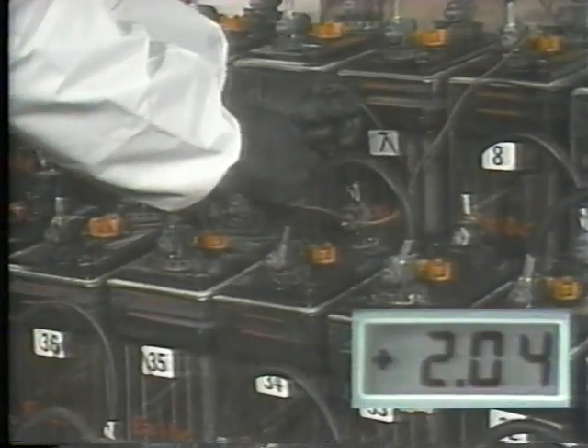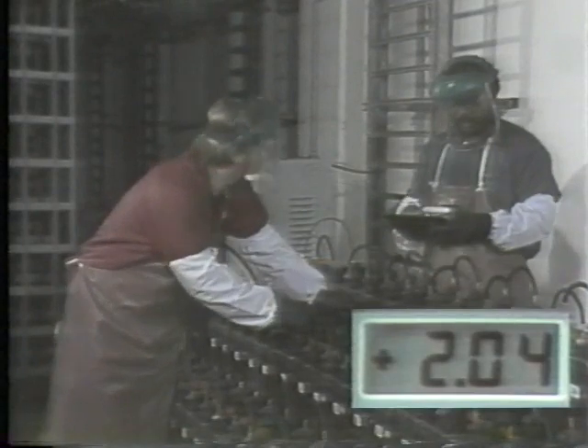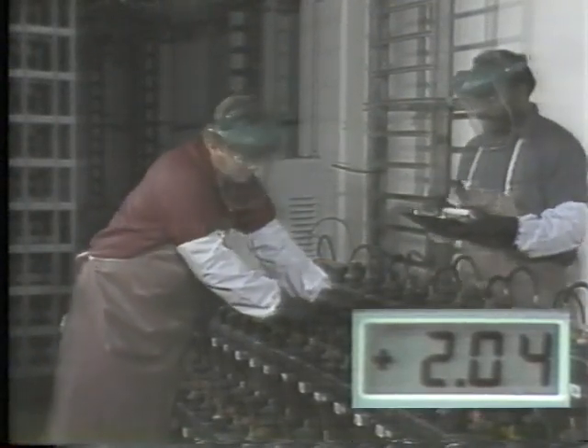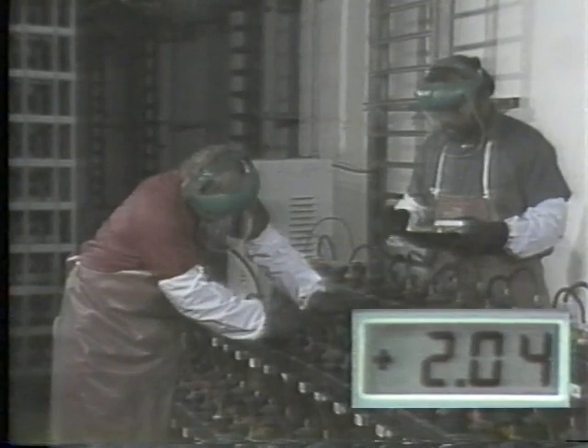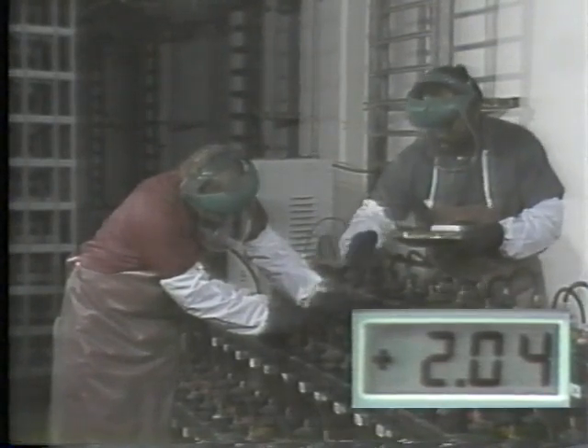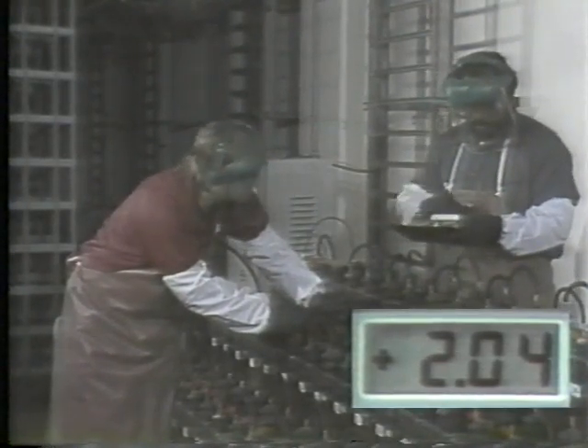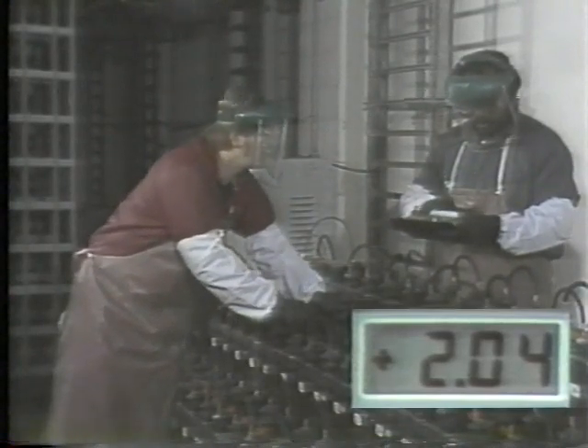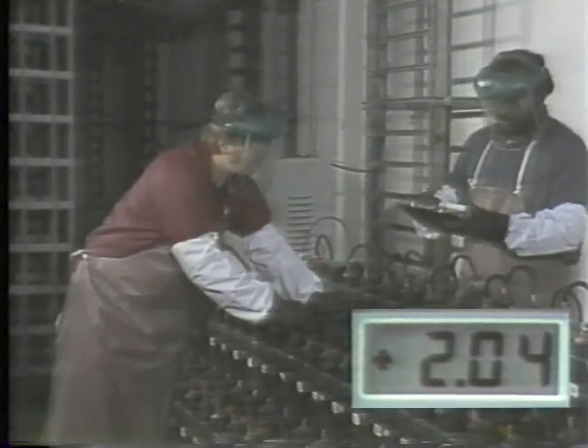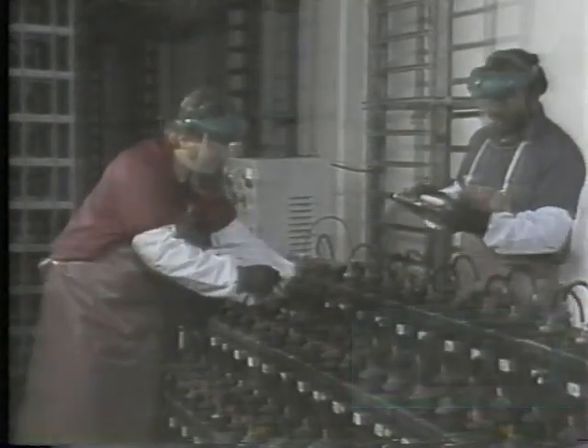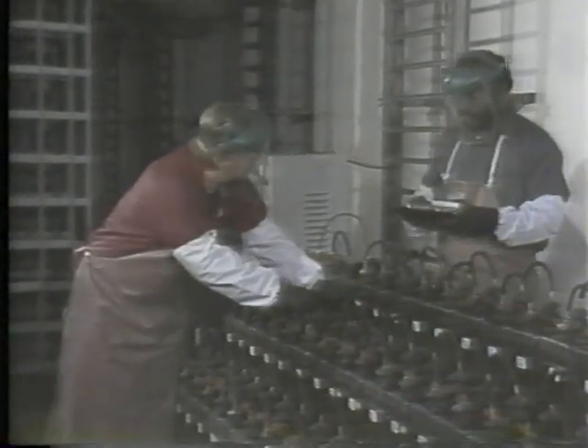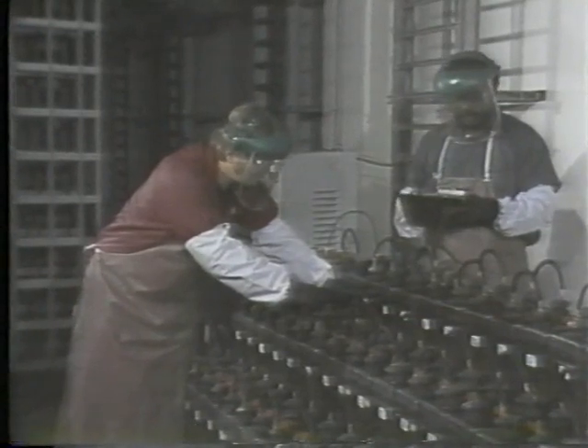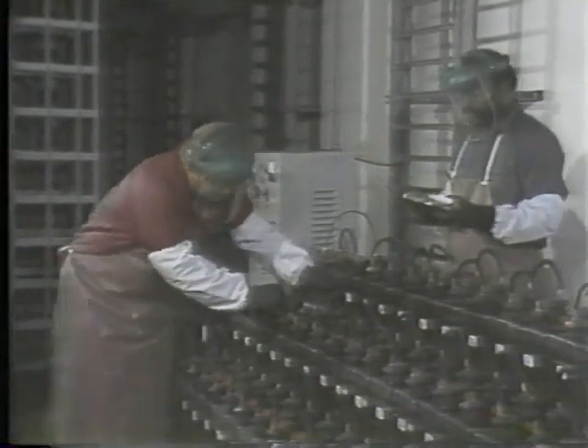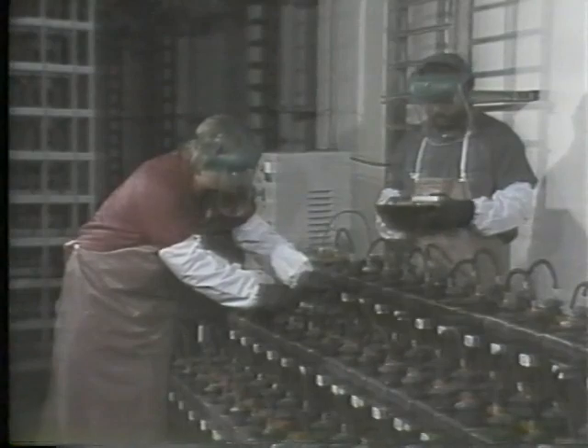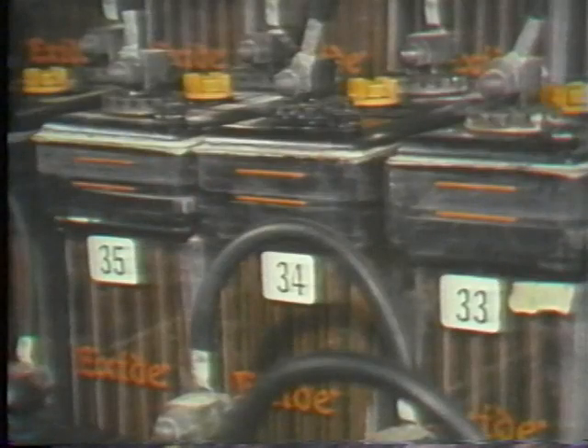But when number 34 is tested, the voltage is low, just as you might expect. Number 34 shows only 2.04 volts, so the cell voltage test backs up the results of the specific gravity test. Cell number 34 isn't taking a full charge. After completing the rest of the cell voltage checks, some corrective action will have to be taken. There are several possible causes for the cell's low specific gravity and voltage readings.